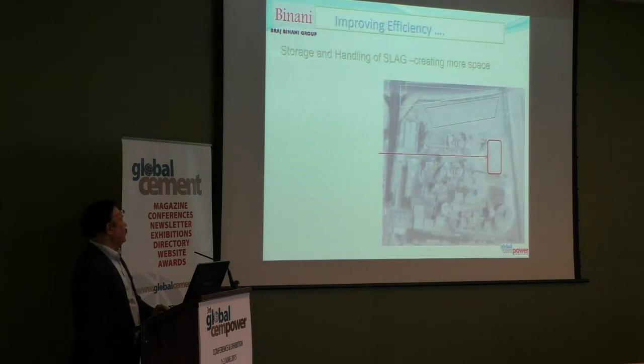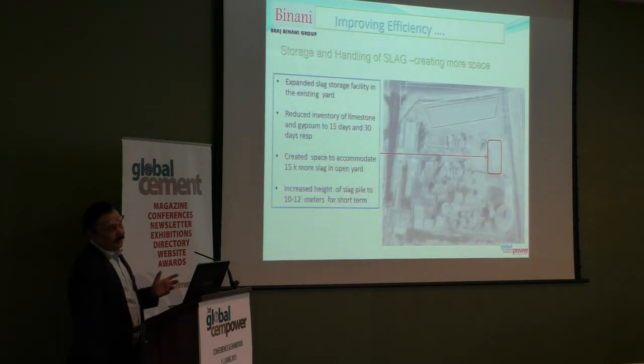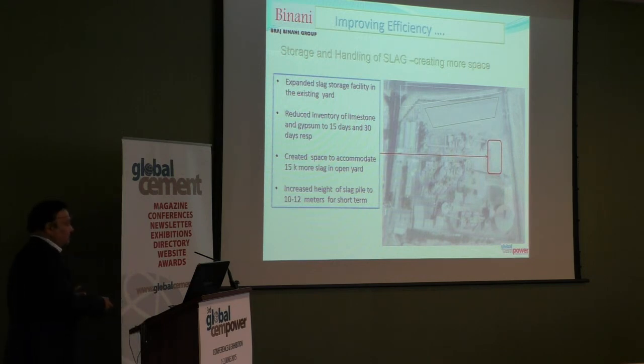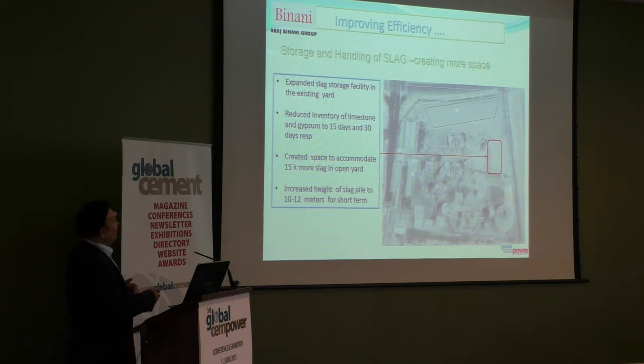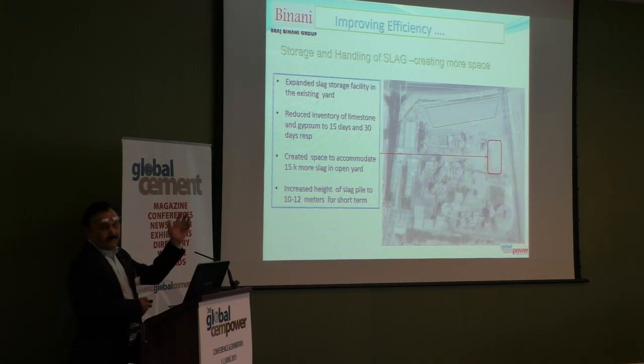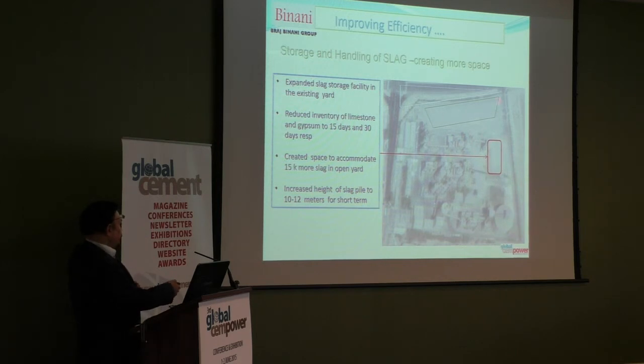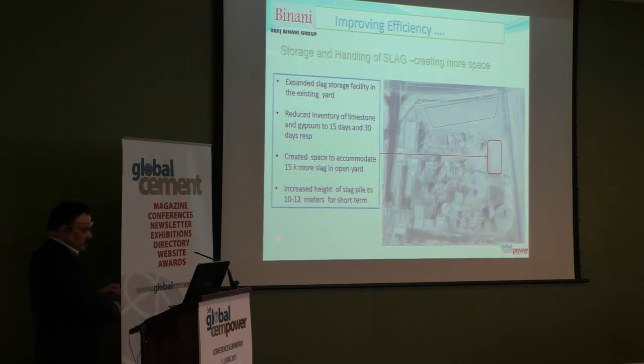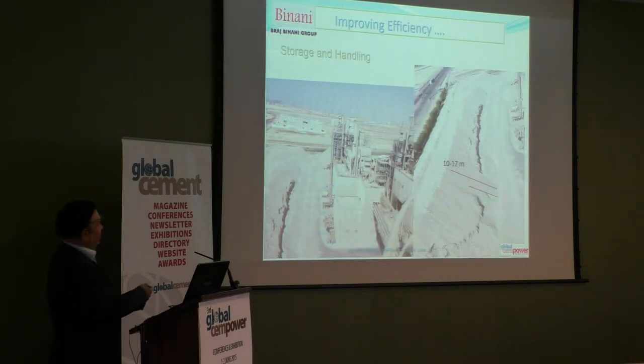What else we did? Because everything is linked to power, it's a grinding station. We also reduced our inventory of 2 materials and created more space for slag grinding. Both limestone and gypsum are locally available. So instead of having 1 month inventory, we reduce it to half. So this land was available, we now use it for drying. One more thing which we did was we increased the height of these piles. This was the original scenario. We increased the height to 10 to 12 meters, creating more space for sun drying. And that's the approach which we use.